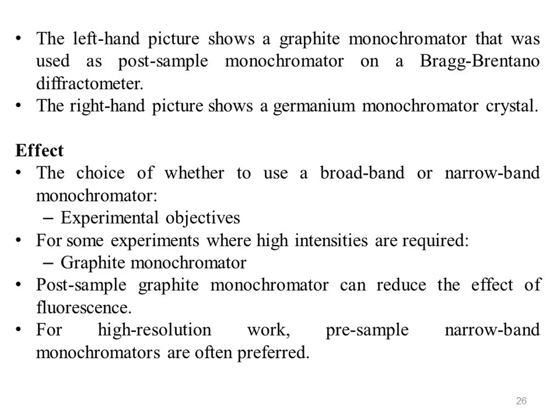What is the effect? The choice of whether to use a broadband or narrowband monochromator will depend on your experimental objectives. For some experiments where high intensities are required, the graphite monochromator will be better. In addition, a post-sample graphite monochromator can reduce the effect of fluorescence from the sample. For high-resolution work, pre-sample narrowband monochromators are often preferred. A comparison of good data obtained with both types of monochromator is shown below.